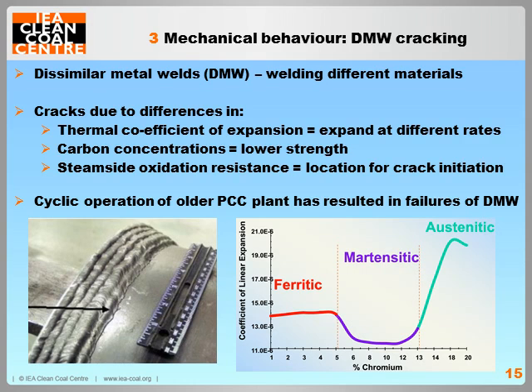Dissimilar metal welds are welds between different types of materials. There is a high risk of cracking at dissimilar metal welds due to differences in material properties. One is the different carbon concentrations cause carbon to diffuse from areas of high to low concentrations, which alter the material properties such that the strength decreases.